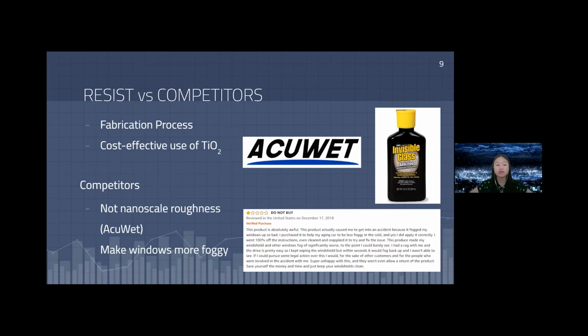However, products like AcuWet don't actually utilize nanoscale roughness. They use larger particles, which means that the water is not dispersed over as large of an area as quickly, and so they're less effective at preventing fogging than we are. And for products like Invisible Glass, there are many problems that include making windows more foggy instead of less foggy. And so our product is unique in that we will be using the nanoparticles and we will be able to make a more effective product.